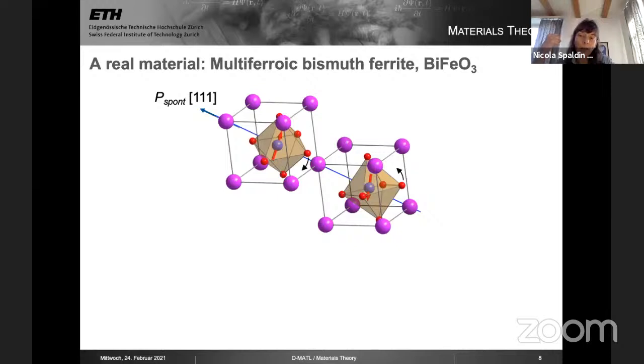So the bismuth shifts by a large fraction of the unit cell along the 1-1-1 direction relative to the rest of the ions. And that gives it a rather large spontaneous polarization along the 1-1-1 direction. So bismuth ferrite is very popular because of this multiferroic property, this combination of magnetic ordering and ferroelectric ordering, both at rather high temperature, which allows it to be used for exotic behaviors, for example, controlling the magnetism with an electric field. Bismuth ferrite is not a new material.